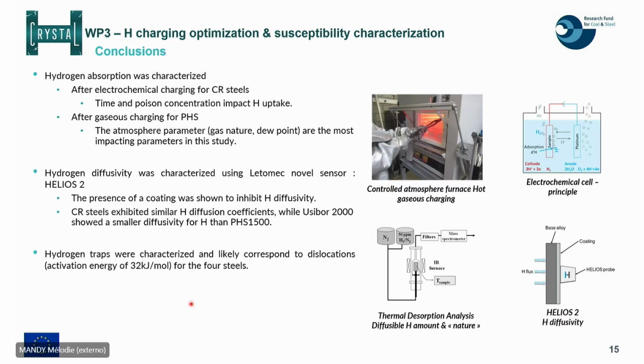So this is the end of the presentation. For the conclusion, we have charged hydrogen in the 4 different materials with more or less difficulties depending on the material. We see that we have some impact of specific parameters like the time and the poison concentration for the cold-rolled steels, like the atmosphere for the press-hardened steels. We were also able to test diffusivity and permeability of hydrogen through those materials with and without the coating through the Letomec sensor Helios 2, and we were able to characterize the different traps that were present in the material as dislocations. So thank you very much for your attention.